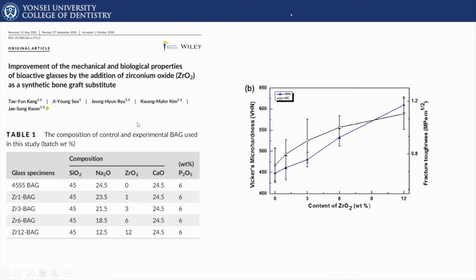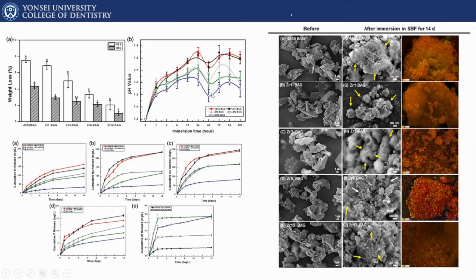We also wanted to improve some mechanical properties in weight-bearing areas. So here we incorporated zirconium oxide into 45S5 bioactive glass to modify the original composition. It certainly improved the Vickers microhardness and fracture toughness as we increased the content of zirconium oxide. And it improved the neutralization of acid, making it into an alkaline environment, and released ions that are responsible for bioactivity. Certainly this release results in a formation of apatite-like structure when they are immersed in simulated body fluid for 14 days. So as you can see here, compared to 45S5 bioactive glass, the bioactivity is relatively well maintained.